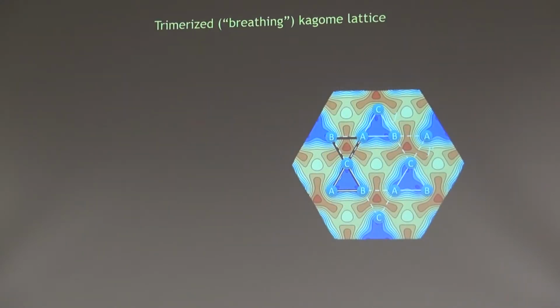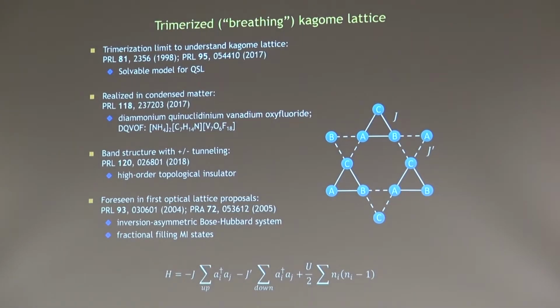So this lattice is also known from condensed matter physics. It's something they call either the trimerized or the breathing Kagome lattice. It was introduced theoretically as a simplification of the Kagome lattice. So since they couldn't figure out what the antiferromagnet in the Kagome lattice does, they instead studied the trimerized Kagome lattice. And it was a very smart thing to do because in the limit of very strong trimerization, this Kagome lattice reduces to a plaquette lattice. So there's basically a plaquette of 3 sites that are strongly coupled. And those strongly coupled sites can be somewhat disconnected from all the other sites. So that means you can start treating this question of macroscopic ordering in this lattice, starting from the microscopic question of what do, let's say, spins do in a single plaquette, and then only afterwards you add a little bit of link from one plaquette to another.